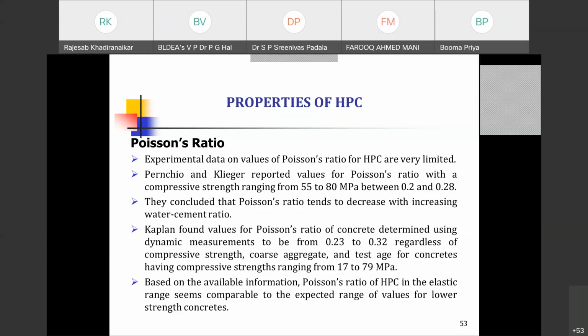Pernchio and Klieger reported a Poisson's ratio for a compressive strength ranging from 55 to 80 MPa between 0.2 and 0.28. And they concluded that the Poisson's ratio tends to decrease with increasing water cement ratio, maybe because an increased water cement ratio means more pores and more micro cracking. And Kaplan found values of Poisson's ratio determined from dynamic measurements lie between 0.23 and 0.32, regardless of the compressive strength and coarse aggregate, and he tested concrete from 17 to 79 MPa. So based on the available information, the Poisson's ratio of high performance concrete in the elastic range seems to be comparable to the expected range of values for lower strength concrete. Not much variation has been observed.